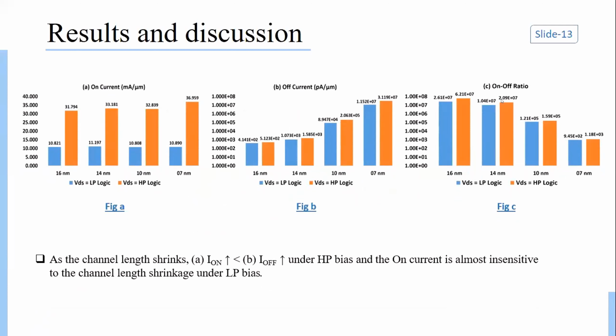From figure A and B, as the channel length shrinks, the increase in the on current is less than that in the off current under HP bias, and the on current is almost insensitive to the channel length shrinkage under LP bias. This is due to the fact that the off current is governed by the DIBL, whereas the on current is limited by the transport mechanism, which depends on the carrier mobility as well as the carrier recombination in the gallium arsenide channel. So when channel length decreases, on-off ratio decreases.